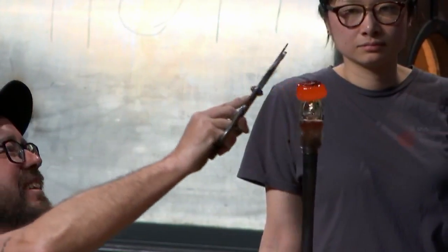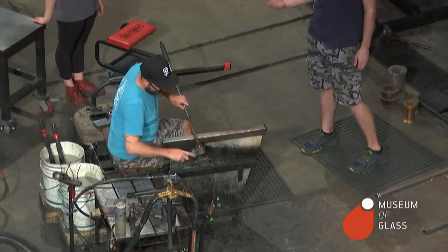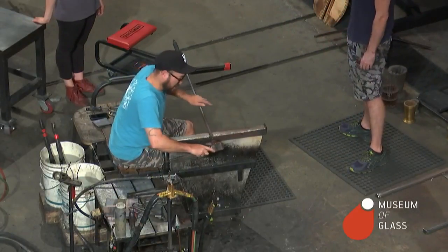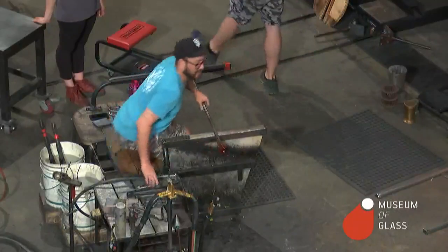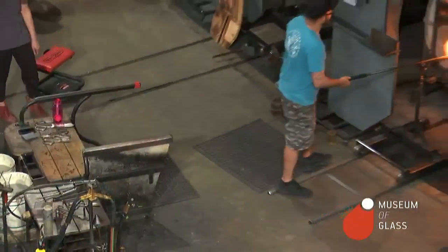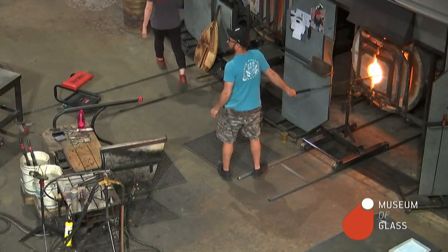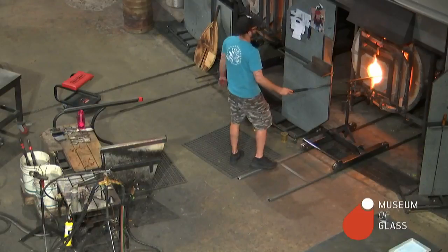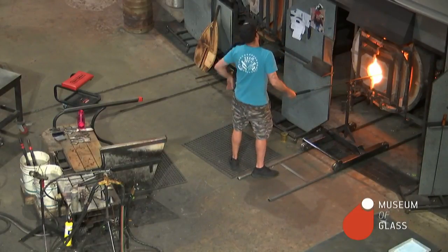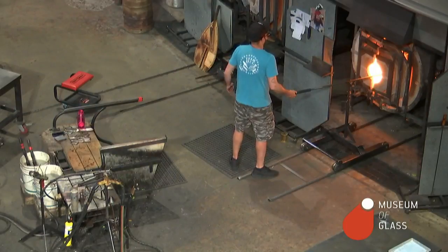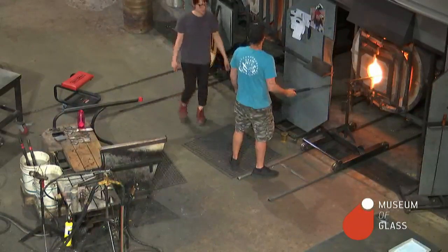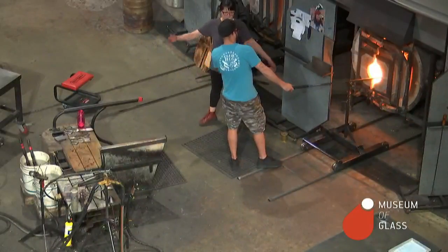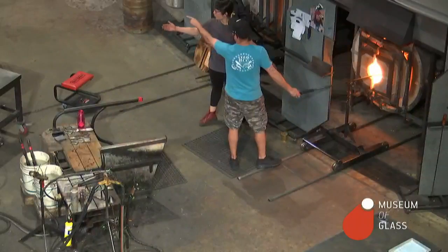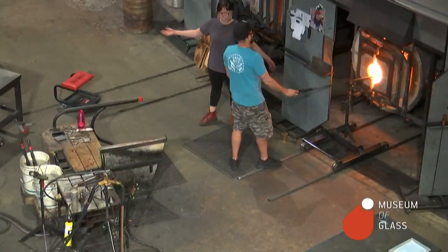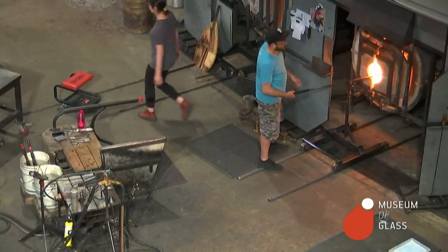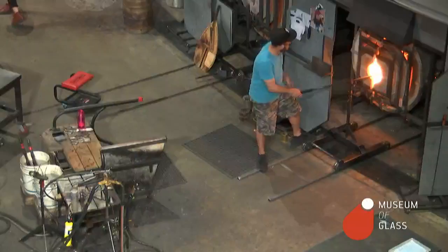So Gabe has dropped the wad of colored glass on top, and now he's going to push it backwards until it entirely coats the original bubble. Color in glass comes mostly from different metals dissolved in the glass when you cook it up from scratch. Cobalt makes glass blue, chromium makes it green, a little bit of gold makes it pink. It's not always the color that you would expect.